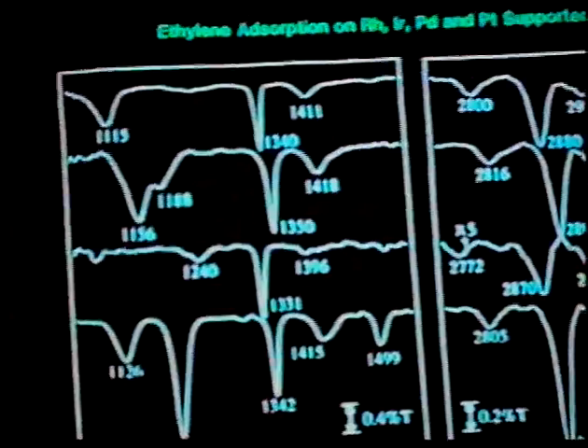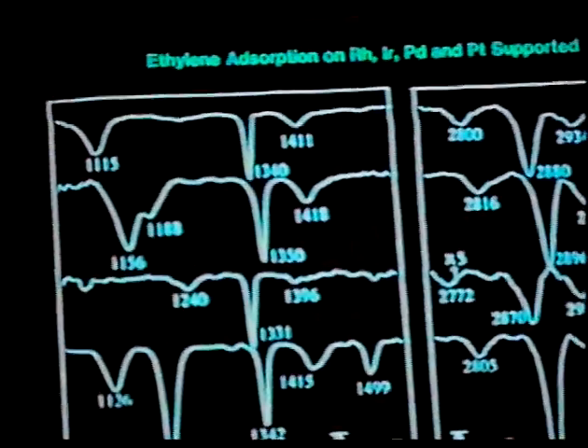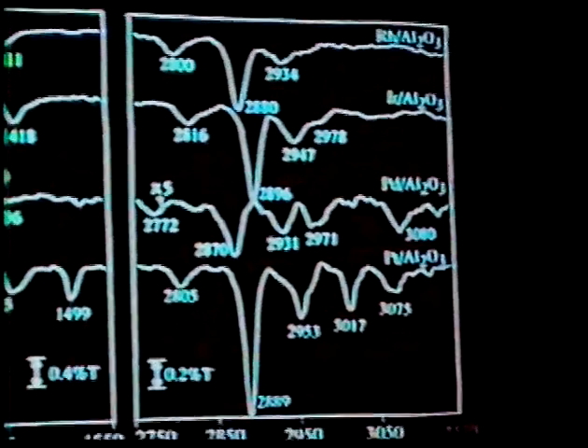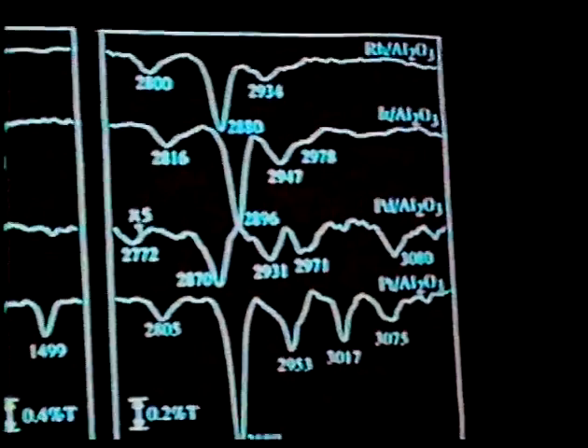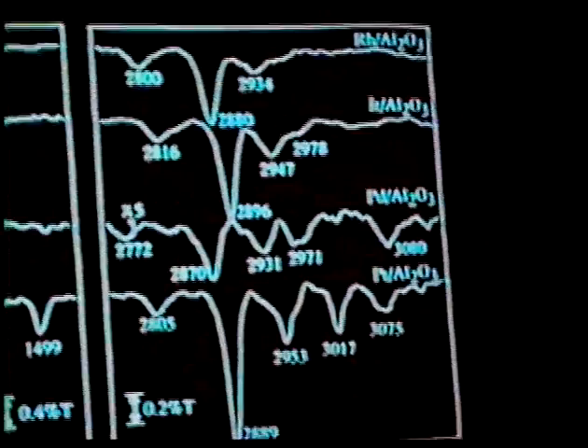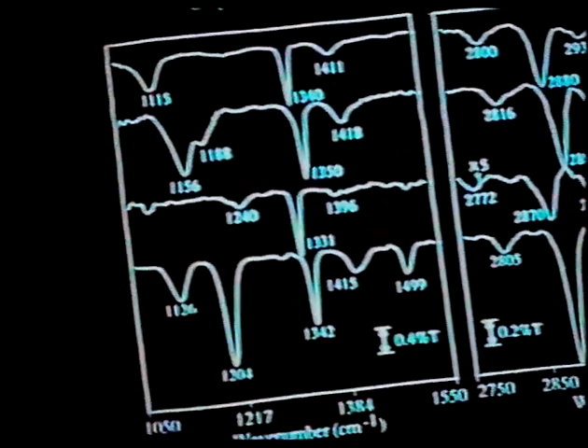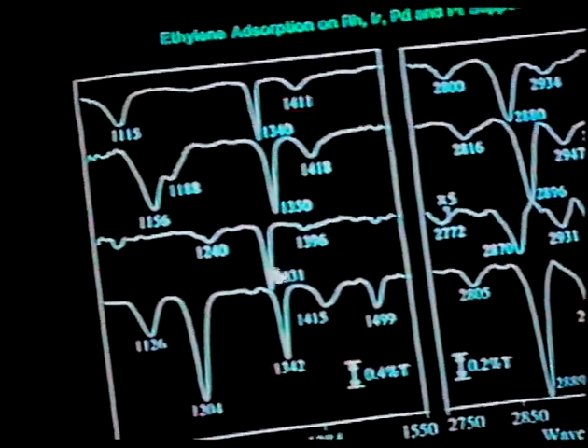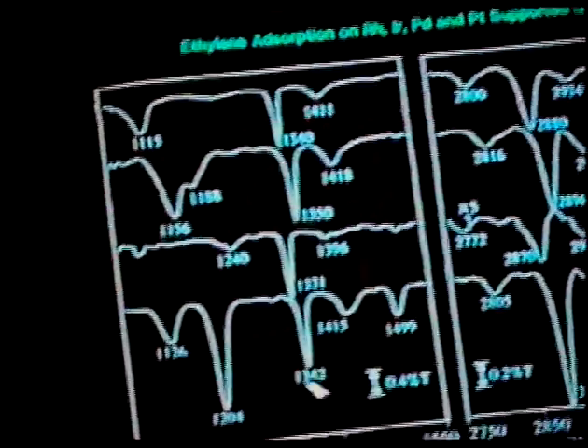what we can do now is begin to extend this work to other kinds of supported metals. What I have here are some results for rhodium, iridium, palladium, and again, the platinum catalyst. These were all prepared to have identical, or as nearly identical as possible, weight loadings and particle sizes. Again, the particle sizes are between 15 and 20 angstroms on average. Samples were prepared so that in the spectrometer beam you have about the same number of sites, the same number of clusters. And what I'd like to point out is that the strength of the ethylene bands, at least this particular ethylene band, is nearly constant throughout this series.